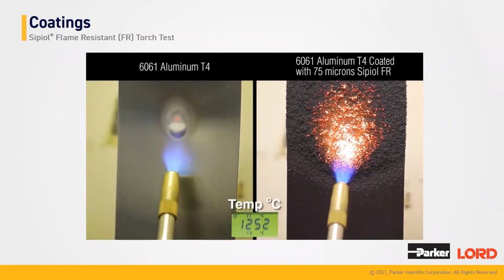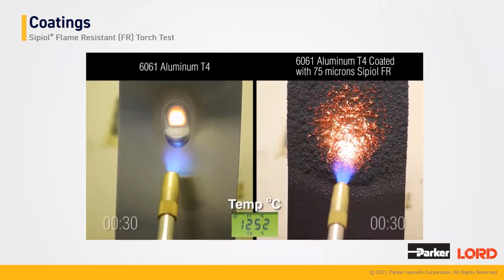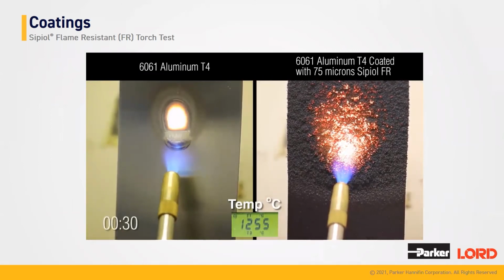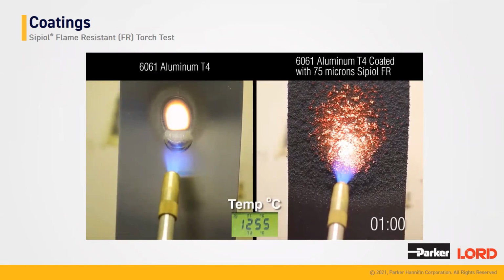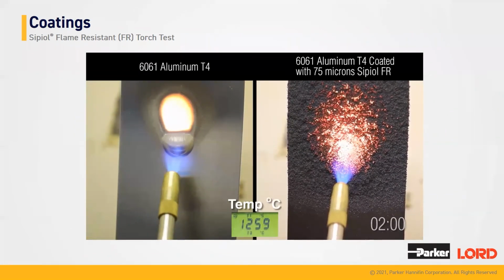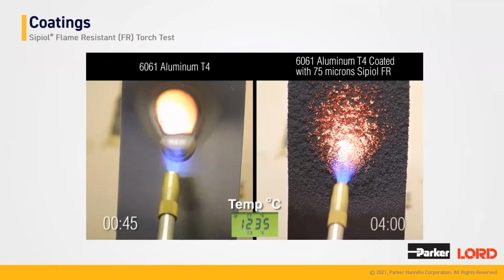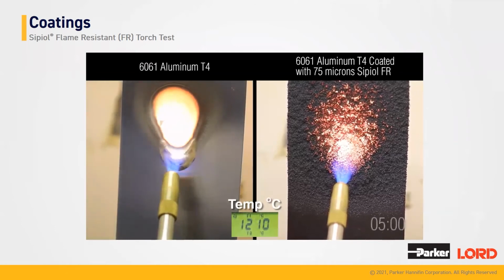We prepared a short video. You can see how Sipiol FR protects a thin piece of aluminum from temperatures up to 1200 Celsius. Without the coating, there will be a hole melted through the aluminum within 15 seconds. But when the aluminum is coated with Sipiol FR, it expands within 5 seconds to protect the substrate. This video only shows results up to 10 minutes, but we ran tests up to 95 minutes without seeing any melting in the aluminum part.